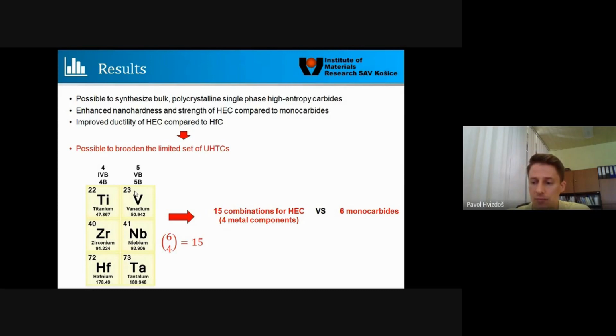So basically what we got is, we were able to synthesize a new type of material. It was in the form of a polycrystalline single-phase material, a so-called high-entropy carbide, which has enhanced hardness and strength, improved ductility, at least compared to the most brittle monocarbide, and at the same time we are able to broaden the limited set of ultra-high temperature ceramics, which was the basic motivation of our work.